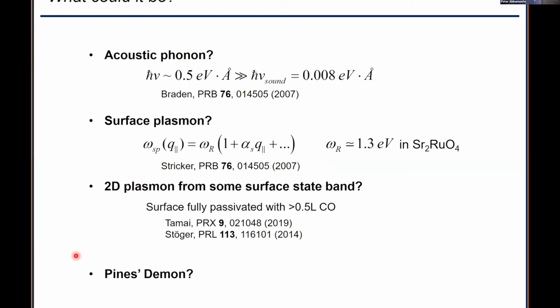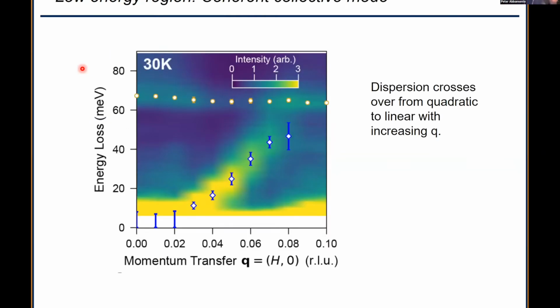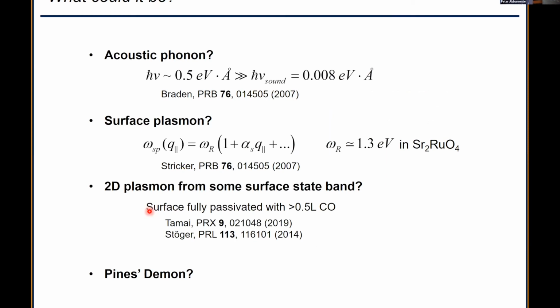So there are kind of 4 things that you could go through to guess what this mode might be. The first guess you might think: is it an acoustic phonon? Acoustic phonons are gapless. Oh, I probably should have said that. The most important feature of this mode is it's gapless. If you go to 0 momentum, the frequency goes to 0. And the dispersion is quite linear, though it seems to cross over to a Q squared at low energy. And that Q squared is real. We spent some time investigating whether that's due to a finite resolution, and that's a real Q squared down there.